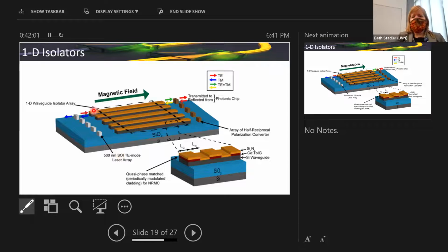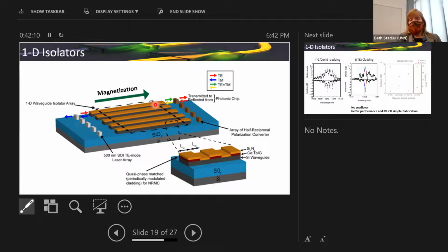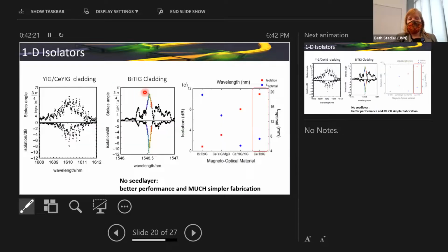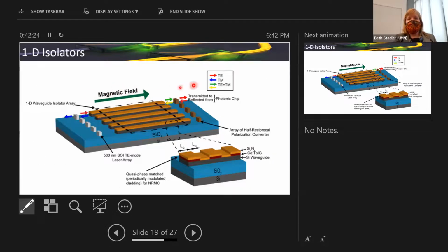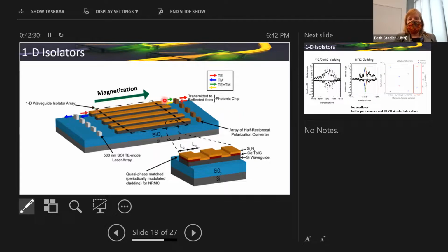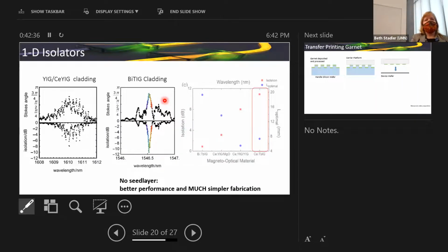The other thing I like about it is it's 1D. And the other thing that turns out, I think, is pretty interesting. We know some people at the Air Force, for example, that are interested in fly-by-light kind of devices, even quantum devices. If you want to put light in, they don't want a magnetic field. Oops, right? They don't want a magnetic field near their other devices. But this is the shape anisotropy direction of these waveguides. So all of these measurements that we've made with David Hutchings are in remanence. We magnetized the sample and we measured it optically without a magnetic field.